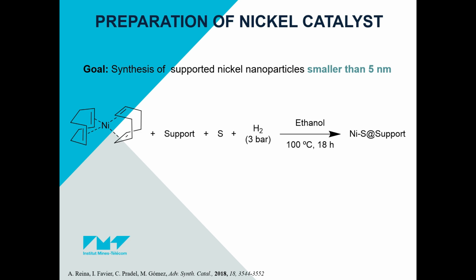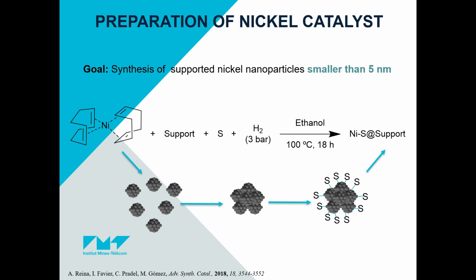For the preparation of these nanomaterials, an organometallic approach was followed, starting from nickel bis(cyclooctadiene) and reducing this ligand with hydrogen, thus releasing nickel atoms, which form clusters that will be stabilized by a stabilizing agent, or in some cases the same support that acts as a stabilizer. These clusters, once stabilized, will be adsorbed onto our support, ending up with our catalytic materials.